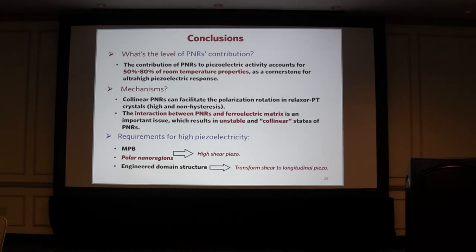So now we can answer the three questions I proposed in the beginning of my presentation. First, the contribution of polar nano regions to piezoelectric activity is about 50 to 80% of the room temperature properties. So it's very important for the high response of relaxor-ferroelectric crystals. And the mechanism is the interaction between polar nano regions and the ferroelectric matrix. Because of this interaction, some energy competition will result in unstable and collinear polar nano regions, and this will make a big contribution to piezoelectric response.